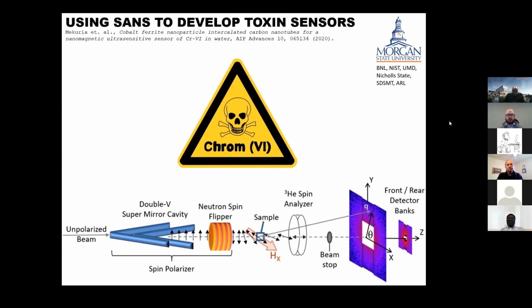And that involves using a neutron spin filter. So the schematic down at the bottom here shows you have an unpolarized beam of neutrons, which means the magnetic moments, or the north and south poles of the neutrons, just think of them like arrows, are directed all over the place. There's no preferred direction. When they go through the double V supermirror cavity, they are preferentially aligned. But then we can flip the spins in a magnetic field, and then it passes through the sample. And then when the polarization of those neutrons is changed by the magnetic structure of the material, we have to analyze that on the scattered beam, and we do that with a spin analyzer.